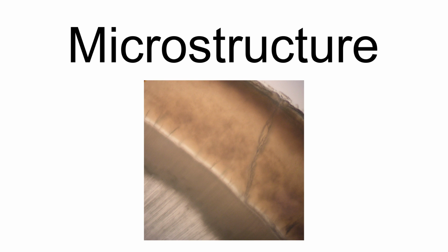The origin of enamel tufts is not fully understood. It appears, however, that they may arise during enamel development in areas where enamel rods are crowded at the boundaries where they are bundled together, creating periodic weakened mineral-reduced planes. These weaknesses then produce transient longitudinal cracks in the transverse plane of the developing enamel. Their formation has been attributed to stress and they are considered a form of defect. However, stress upon the enamel is not needed to produce them since they occur in impacted third molars that are not affected by biting forces.